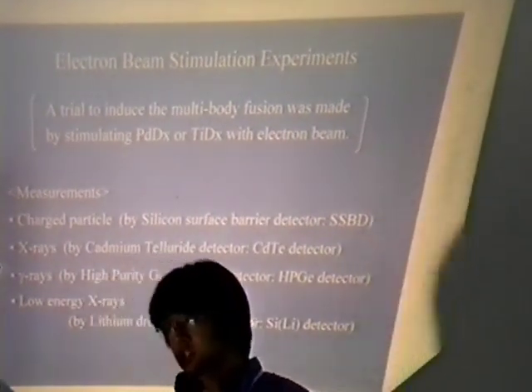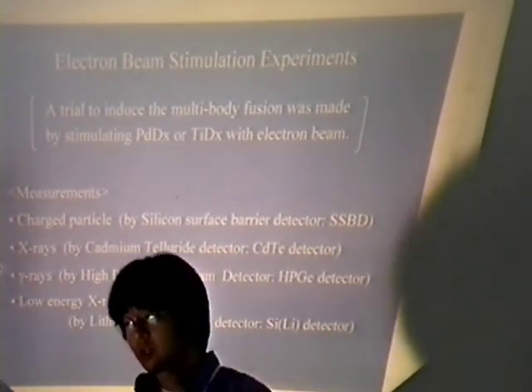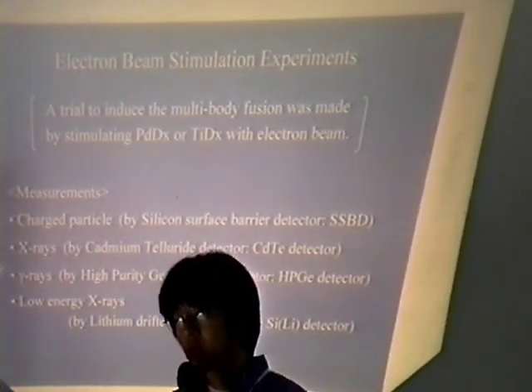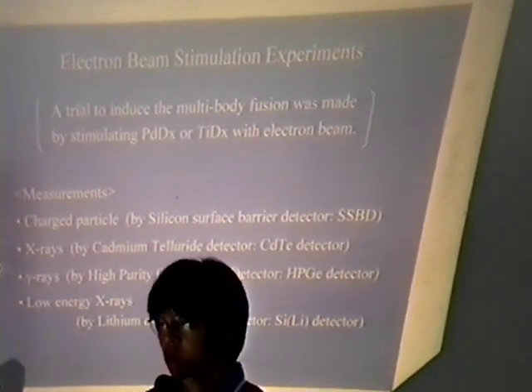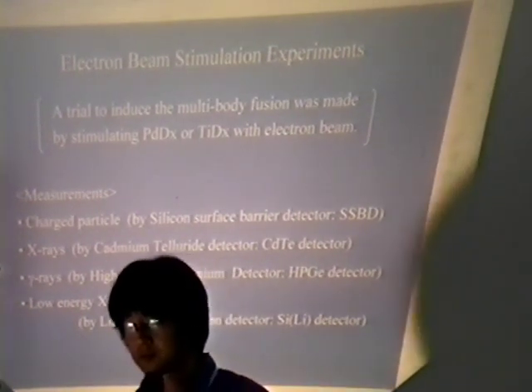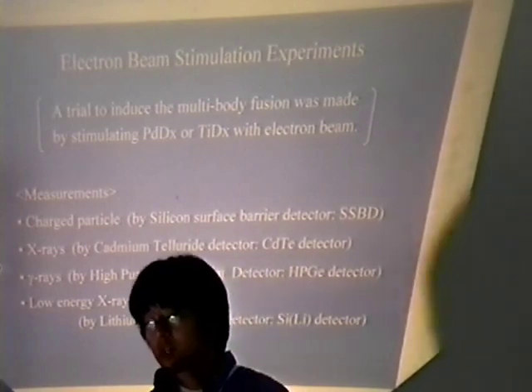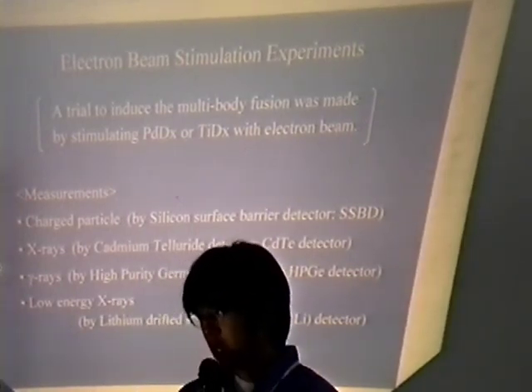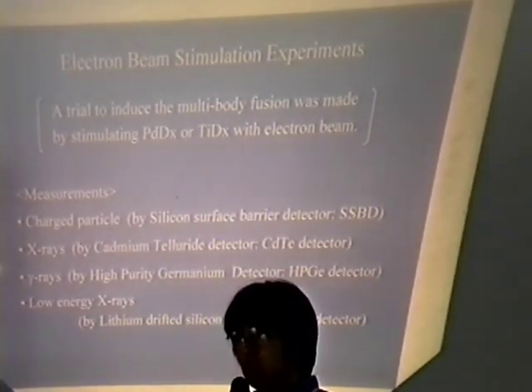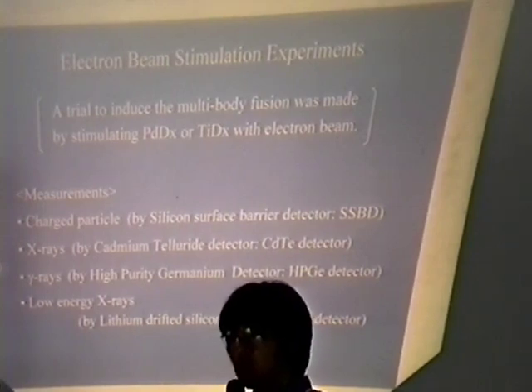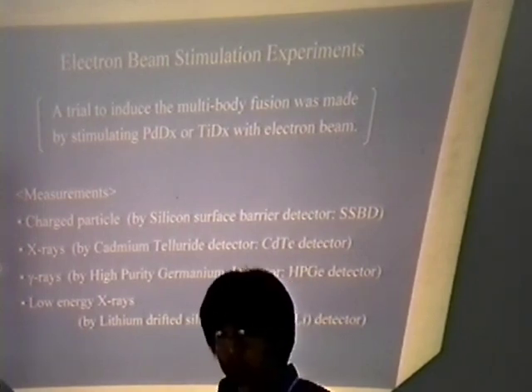Next, I show the electron beam stimulation experiments. This experiment is a trial to induce multibody fusion by stimulating PdDx or TiDx with an electron beam. Measurements of charged particles, X-rays, gamma rays and low energy X-rays were performed during the electron beam irradiation.